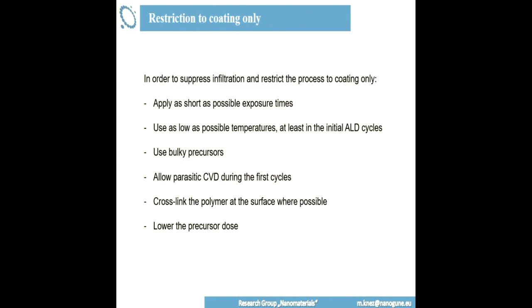Okay, so this was infiltration. If you want to restrict your process to coating only, so you don't want to have an infiltration, you just want to coat, of course, you need first of all to apply as short as possible exposure times. That means you want to restrict the binding only to the surface. You don't want to allow the particles to go into the polymer. Then, if you use as low as possible temperatures, you are way below the glass transition temperature, which helps to prevent also the precursor from penetrating into the polymer. If you use larger precursors, they will absorb into the polymer and dissolve more slowly, which means also bulky precursors are going to help you to restrict to coating only.